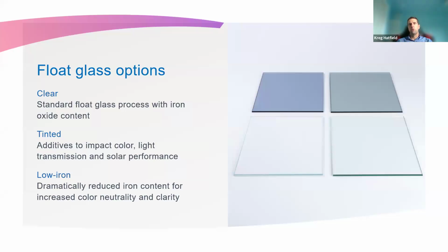If everybody's familiar with the older buildings in the United States, you see a lot of bronze, dark gray. The reason those have those heavy tints on there was because before low E coatings really had changed and become very diverse, you would drive down the amount of visible light and the solar heat gain by those tints, and then still apply either a hard coat or soft coat on there to drive down those solar heat gain numbers. But now that we've been able to revolutionize some of the low E coatings that are applied on the building, we don't have to use those heavy tints as much as we have in the past.